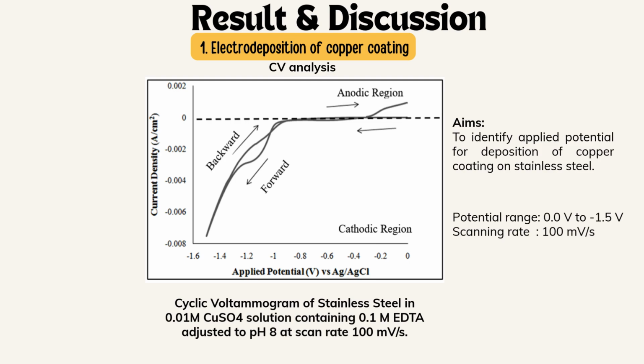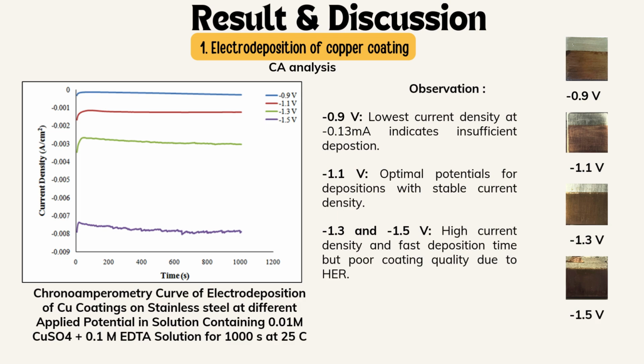Moving on to the results and discussion part, firstly is the CV analysis, which aims to identify the applied potential for deposition of copper coating on stainless steel. Next is the CA analysis. Based on the CV analysis, the deposition potentials of negative 0.9 volt, negative 1.1 volt, negative 1.3 volt, and negative 1.5 volt were chosen as the applied potentials for deposition of copper coating on stainless steel.